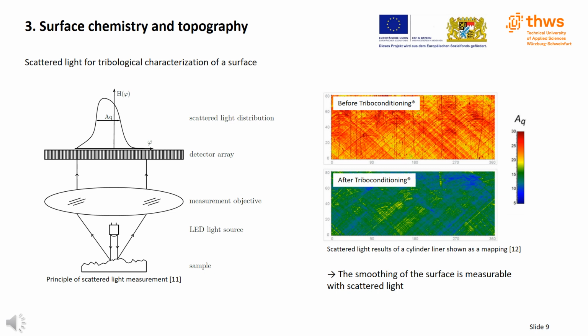The scattered light parameter AQ corresponds to the variance of the scattered light distribution. Because the scattering angles are evaluated, AQ is a measure of profile slopes. The lower the AQ value, the shallower the slopes of the profile are, meaning the surface is smoother. The figure on the right shows the results of a scattered light mapping on a cylinder liner. The surface before triboconditioning is shown at the top and after triboconditioning at the bottom. Before triboconditioning, the AQ values are between 20 and 30. After triboconditioning, AQ values between 10 and 20 are achieved. The AQ value is almost halved, which indicates significant smoothing.